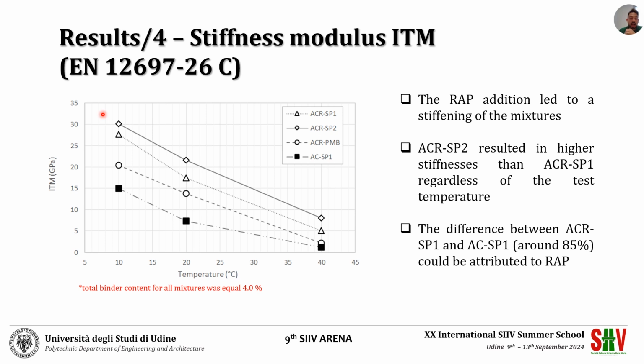Finally, I want to emphasize the differences between ACR-SP1 and AC-SP1. These two mixtures have the same composition except for the use of solely virgin aggregate in the latter. The difference between the two mixtures is around 85% as it is due only to the RAP.